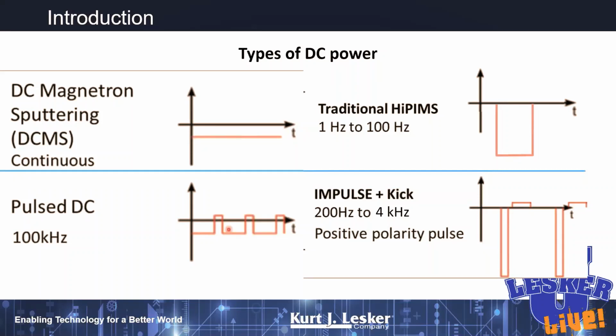So if we have a pulse like this, then we have to have sort of an off period there for the target to recover thermally before we pulse it again. And so with HiPIMS now we can have massive pulses to the target, but then we're going to have relatively long off periods for the target now to thermally recover before we pulse it again. And so in traditional HiPIMS, with pulses which are on the order of maybe 2 orders of magnitude larger than the pulses here, we dramatically increase the fraction of sputter target atoms or molecules that get ionized. And if we start sending ionized sputter material at our substrate, we get lots of interesting effects of morphology.